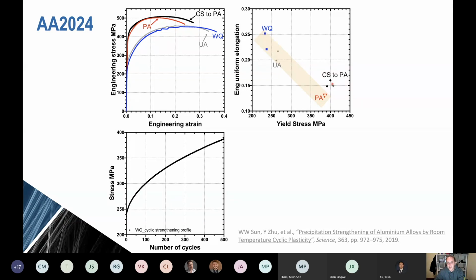And that's pretty interesting. It tells us that if you could develop a way to apply such cyclic plasticity industrially, then maybe you don't need to apply elevated temperature thermal treatments to aluminium alloys at all. Some companies are pursuing this using ultrasonics, high energy ultrasonics, and we're working with some of them in this area, and it seems that it will indeed work. So it's a very interesting thing.